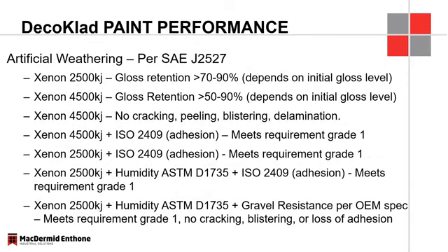Weathering, so there's artificial weathering, which is xenon testing, performed at both 2,500 and 4,500 kilojoules. And these are combined with tape test for adhesion. We look at gloss retention. We're looking at combining it with humidity, gravelometer, gravel resistance. So very stringent test performance that these coatings need to meet in order to pass.